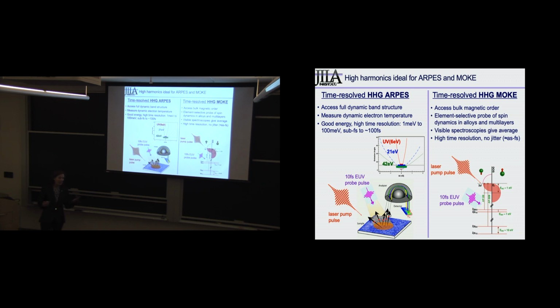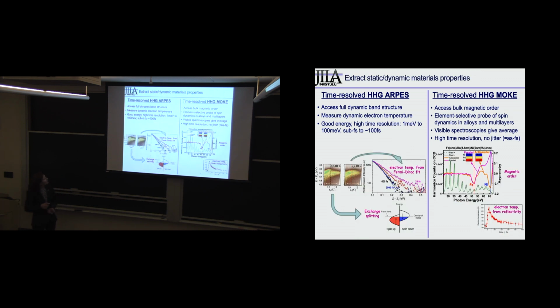With angle-resolved photoemission, that you have the beautiful setups here, you're looking at the surface. This is what we can measure. For example, the electron temperature by taking a line out at the Fermi edge, and we fit to different temperatures. We can measure the exchange splitting when we can see it, and that is at the surface. And then with the magneto-optic spectroscopies, we measure the bulk magnetic order, and we can also measure the on-resonance electron reflectivity and extract the electron temperature. So we have two ways of seeing that we're measuring the right electron temperature using two very different techniques.